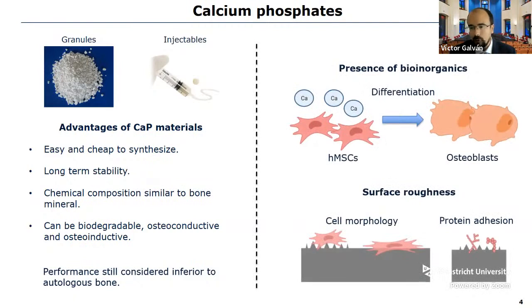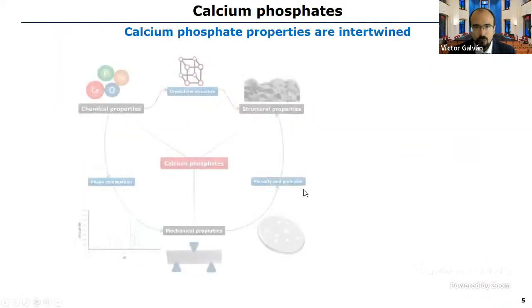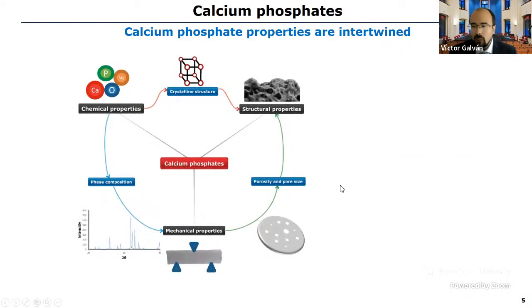What we know about the performance of calcium phosphate is that it depends on the material properties. For example, the presence of bioinorganics can trigger the differentiation towards the osteogenic lineage, and the surface roughness is known to affect, for example, cell morphology or protein adsorption. Therefore, it is really important to know the exact role of each material property in the bioactivity of the calcium phosphate. And this is difficult to achieve because these properties are not independent, they are intertwined.